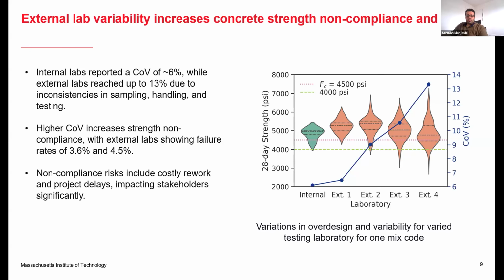And we can see that the higher variability directly translates to increased non-compliance rates, with external labs showing failure rates of 3.6% and 4.5% compared to internal labs. These non-compliance risks create substantial business impacts, including costly rework and project delays. And the coefficient of variation across different labs is different as well, as you can see in the blue lines in this figure.